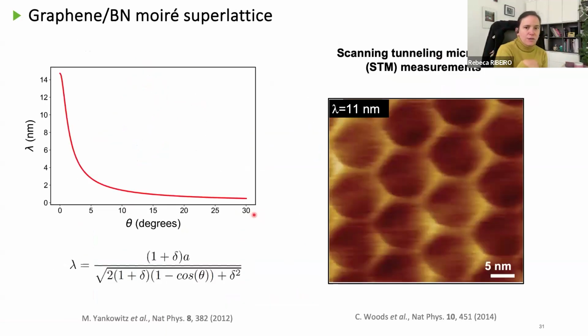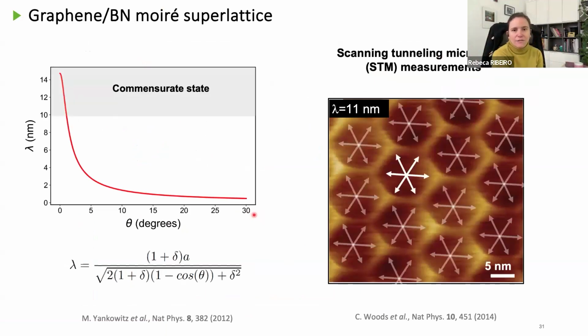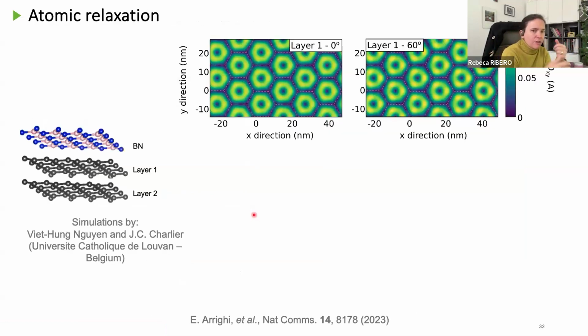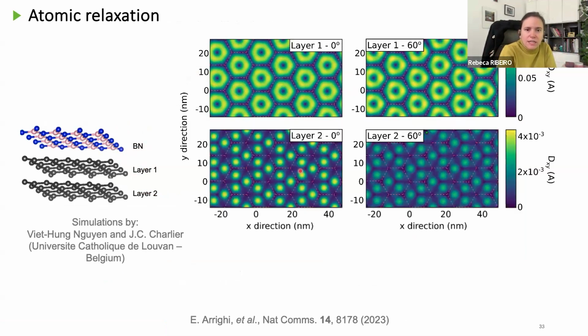However, if we remember before, when I was telling you that there is this commensurate state where you have all the strain distributed, we think that this commensurate state might be at the origin of this difference. So we asked our collaborators in Louvain-la-Neuve to make numerical simulations of what's happening to each one of these layers. How is this commensurate state? So if we look at the first layer, the one that is closest to the boron nitride, we don't see almost any difference. Now, if we go to the second layer, we can see that there are a few differences between them.